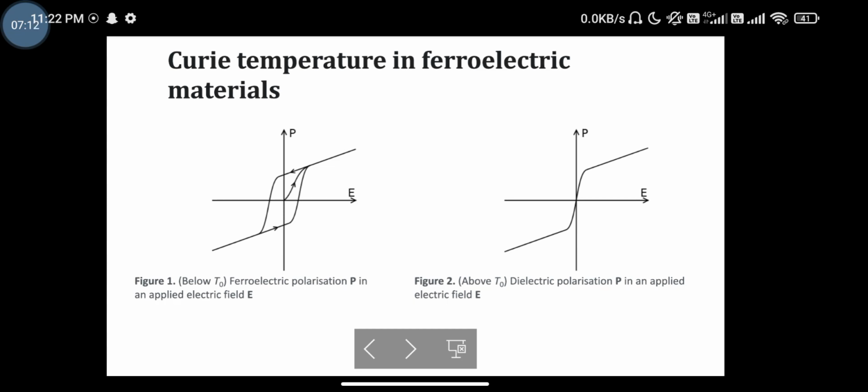In the case of a second order transition, the Curie Weiss temperature T0, which defines the maximum of the dielectric constant, is equal to the Curie temperature. However, the Curie temperature can be 10K higher than T0 in the case of a first order transition. In ferroelectric dielectrics, materials are only ferroelectric below their corresponding transition temperature T0.